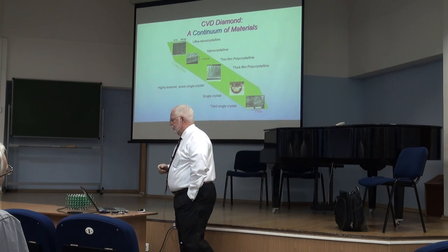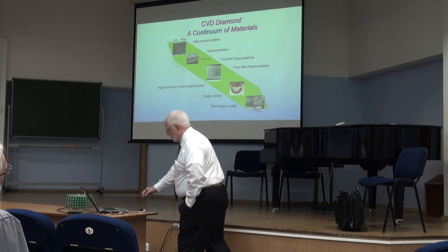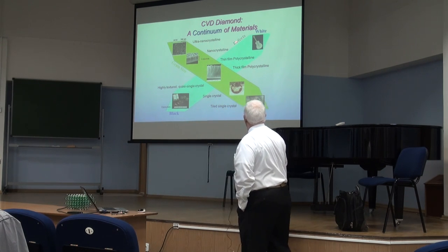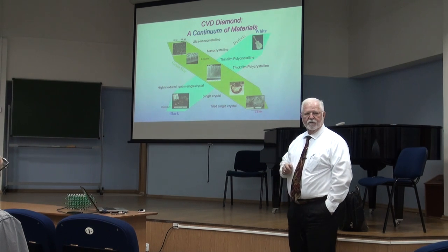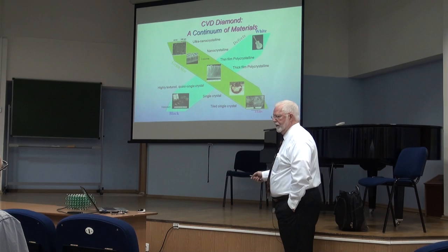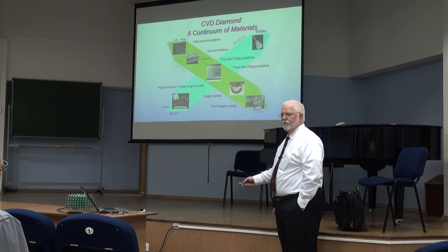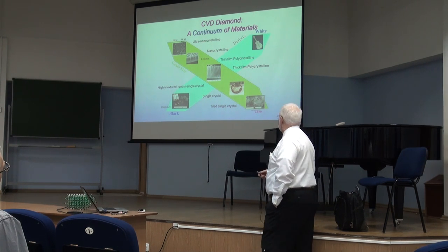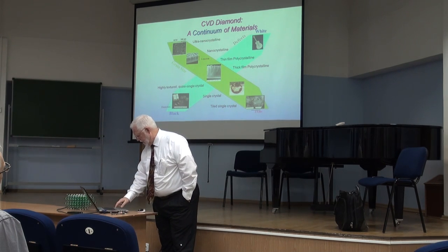Now, there are many other dimensions in this continuum. Another general dimension could be, say, defect structure. If you grow diamond very slowly, you can grow very white, clear diamond that has very few defects in it. Or if you grow it much faster and therefore more economically, you can still get high thermal conductivity, but now it looks grayish black, and that has more applications either in cutting tools or thermal management. And there's a whole series of other axes one could plot on that.